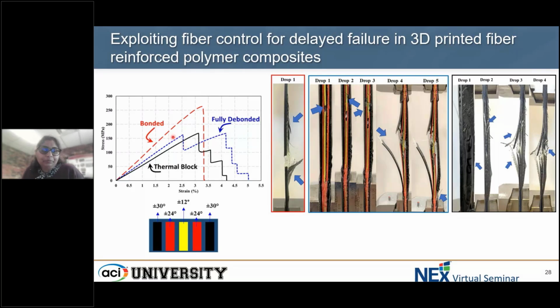The thermal block, which is more in terms of the 3D printing process itself, showed a nice progressive failure. Though the load did not increase after the first drop, we still saw that the other layers were maintaining that load for a certain amount of strain percentage. So in this first design, a fully debonded configuration got us up to 5% strains, although at compromised loads, but we still have a better configuration compared to the fully bonded type.